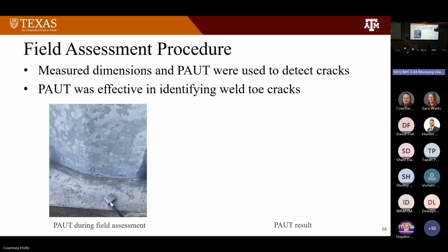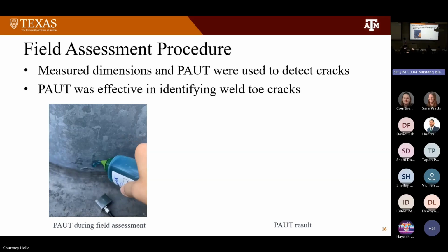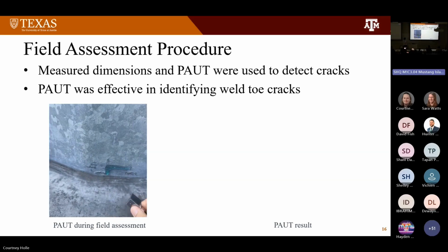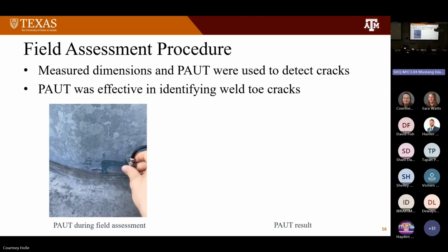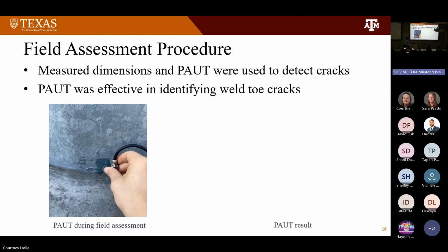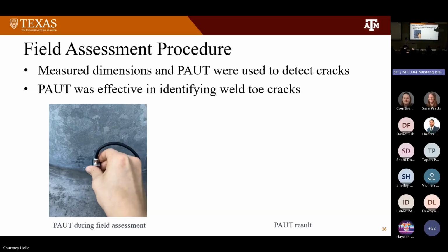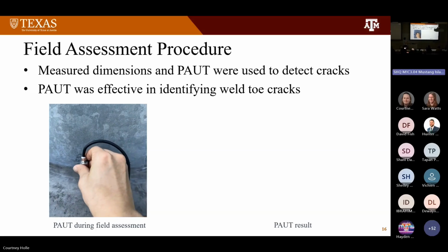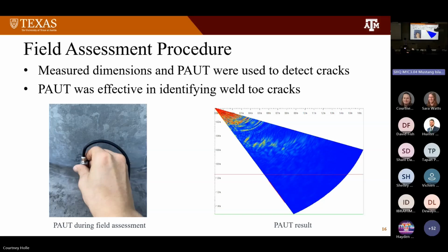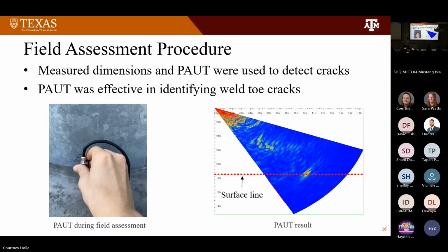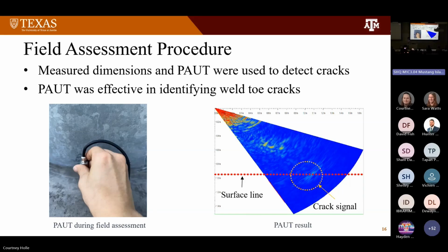So here is the video of the field assessment. First, we apply couplant gel on the surface, and then attach the probe on the surface and move across the region of interest. And then we can get these kinds of results. This is the result of the PAUT. We already measured the thickness of the pole, so we know where the surface line is. So if the signal comes around the surface line, that's how we find where the crack is. And these images allow us to measure the crack size.